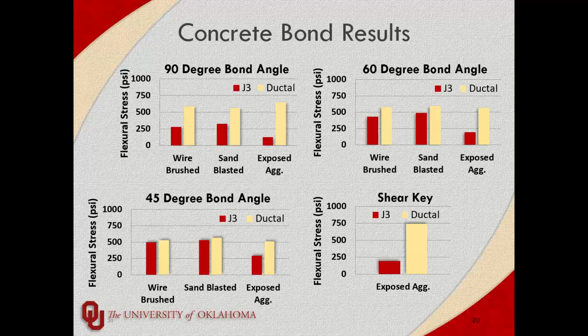And for the J3 that we tested, the bond angles that were best were 45 and 60 degrees. They performed very similar to the Ductal, even though they did fail at the interface. But one thing we noticed, while they failed at the interface, they were very similar to the monolithic strength of just the conventional concrete. So we counted that as a win. It would make sense that the weak surface would be the interface.